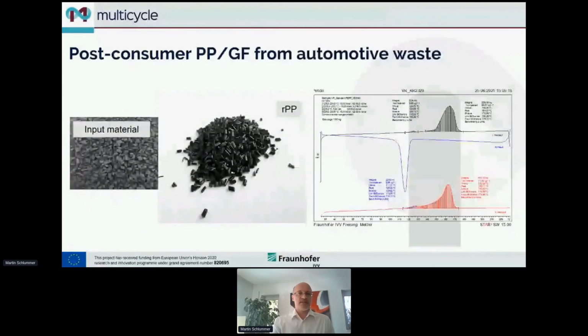Polymer wise, here just examples. The in-feed material for polypropylene. You see here the recovered one, really free of any glass fibers, and here you see the resulting DSC curves, and a very, very clean one. You do not see any other polymer in here. So it's a very, very good result for us.